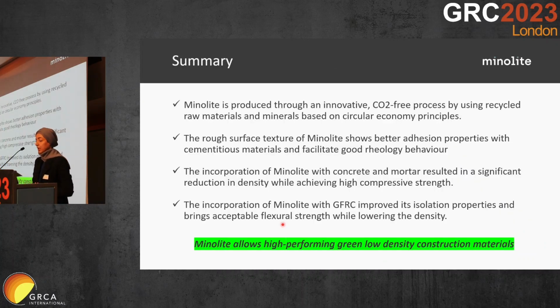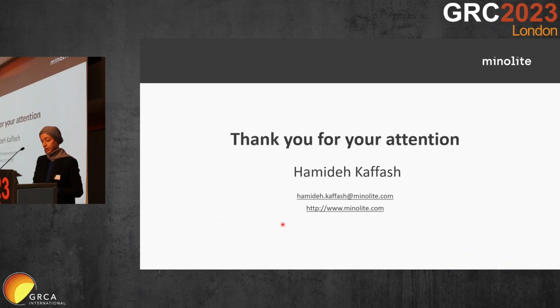To wrap up, Minolite is produced through an innovative and CO2-free process by using recycled raw materials and minerals. The rough surface texture of Minolite shows better adhesion properties with cementitious material and facilitates good rheology behavior. The incorporation of Minolite with concrete and mortar resulted in a significant reduction in density while achieving high compressive strength. The incorporation of Minolite with GFRC improved its insulation properties and brings acceptable flexural strength while lowering the density. And Minolite allows high-performing green, low-density construction material. Thank you for your attention.